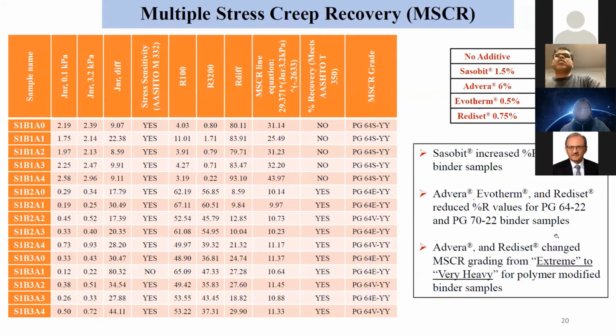Next, we're going to talk about multiple stress creep recovery. There we found that Sasobit increased the percent recovery, whereas the other additives, Advera, Evotherm, and Rediset, reduced the percent recovery for a couple of binders, 64-22 and 70-22. Also, for some of them, Advera and Rediset mostly changed the MSCR grade of the binder without adding additives. It was extreme.